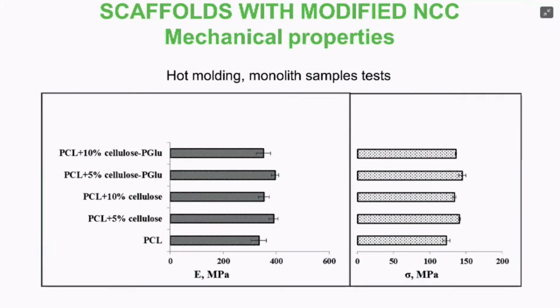First of all, we wanted to test what it actually improves in the mechanical properties of polyester materials. So we prepared, with the aid of our colleagues, samples of polycaprolactone mixed with neat cellulose, here and here, 5 and 10%, and mixed with polyglutamic acid modified cellulose. So we could say that these tests showed us Young's moduli and compressive strength here.